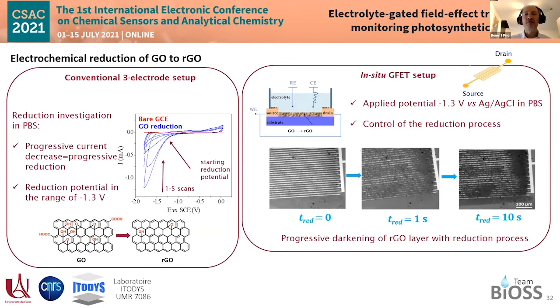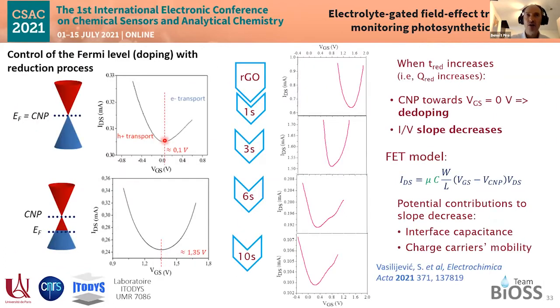What is interesting actually is if graphene has a Dirac point, that is the point of minimal current between the hole transport side and the electron transport side, reduced graphene oxide has a Dirac point which is quite far from the 0 volt gate voltage because of residual doping. And actually that electrochemical reduction allowed us to select our level of reduction depending on the charge passed through the transistor, through the reduced graphene oxide, or time of reduction. Okay, so we can adjust the position of the Dirac point that way, and adjust actually.